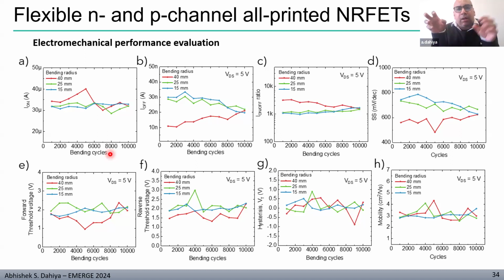The reason is that we are doping source and drain to make them N-channel or P-channel, and the doping helps to make better semiconductor-metal contact because you are making your metal connection onto the doped part of the ribbon. The doped part is like a degenerate semiconductor which acts as a metal, so you are forming a junction between metal and metal. So once you form good ohmic junctions, your charge transport is efficient, you have less losses at the interface, and that's why the performance is better for top-down approach materials.